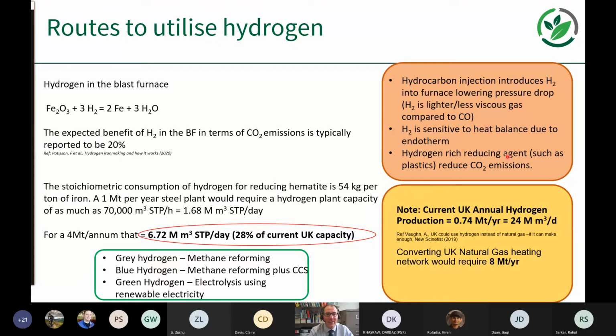So the hydrogen in the blast furnace, although it reduces pressure drop in the blast furnace, which is beneficial because it's lighter and a less viscous gas compared to carbon monoxide, the reduction of iron by hydrogen is endothermic, so it has a heat requirement. So it affects the heat balance, which limits the overall amount of hydrogen that you can put directly into a conventional blast furnace.